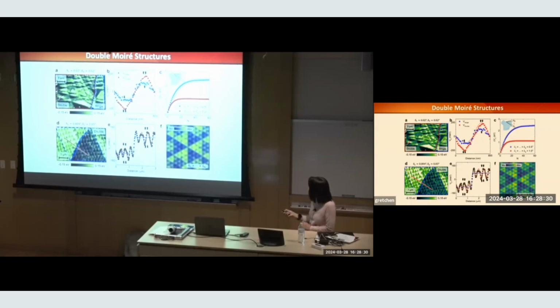But what if the two interfaces have different twist angles? Then you have this bigger triangle on top of that smaller triangle. The bigger triangle gives you a potential that's basically flat, and the smaller triangle gives you this dominantly sinusoidal pattern. And now you have a ferroelectric material that gives you multiple levels of ferroelectric potential. So all with hBN just folded or stacked, right?